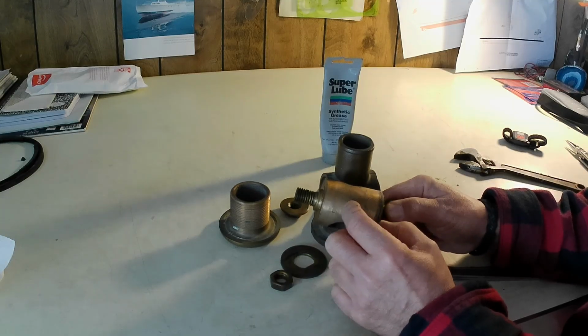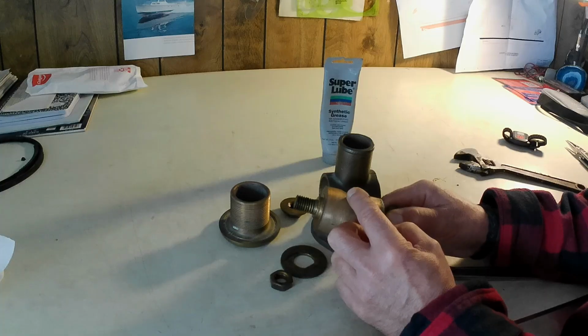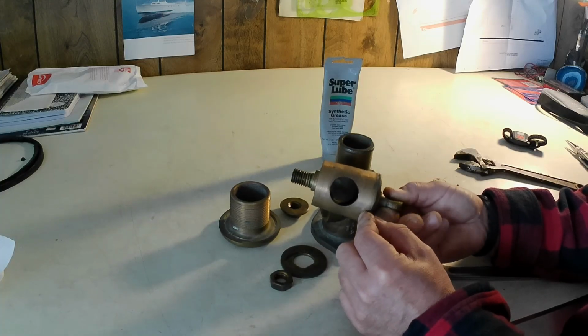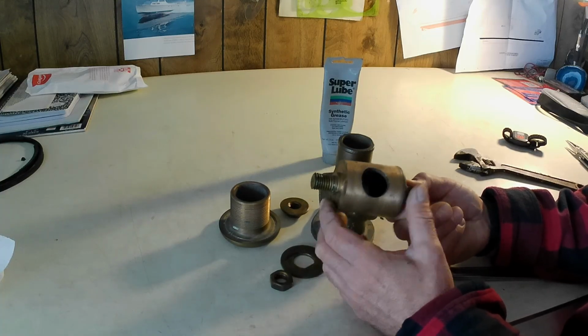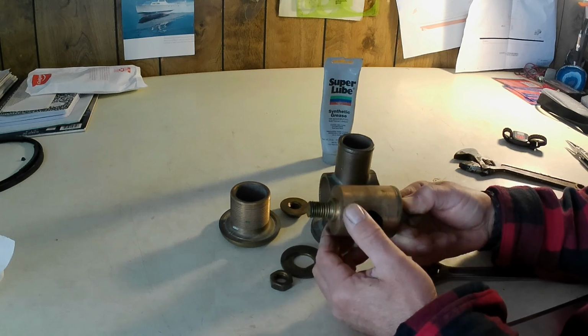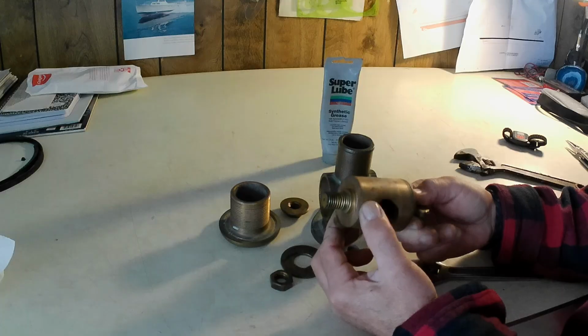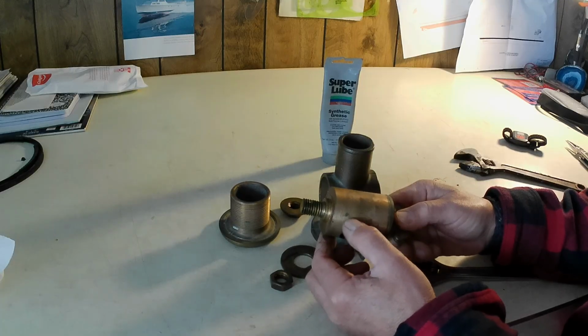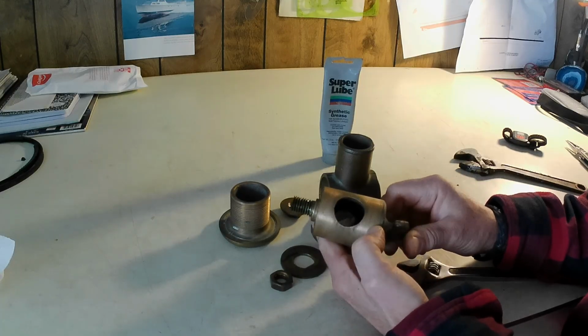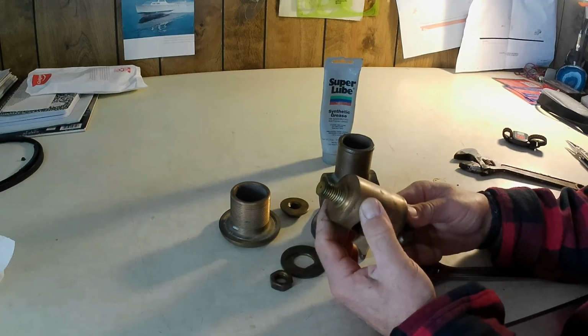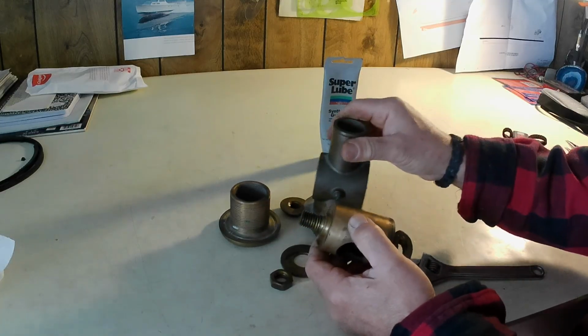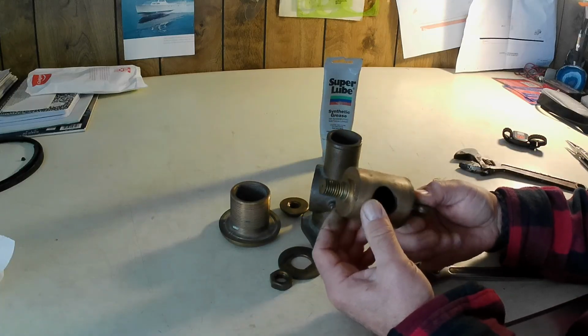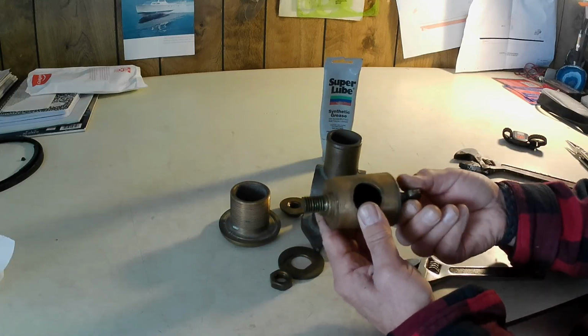As long as that is in the center of the valve, it's not a problem. When you start to get corrosion around the 2 edges outside of the opening, then you're getting into a situation where this valve may start to drip. That is actually what happened to the head discharge, which was this identical valve actually, before the head on Charis was replaced with the airhead.